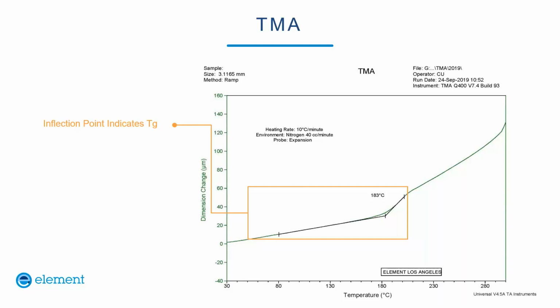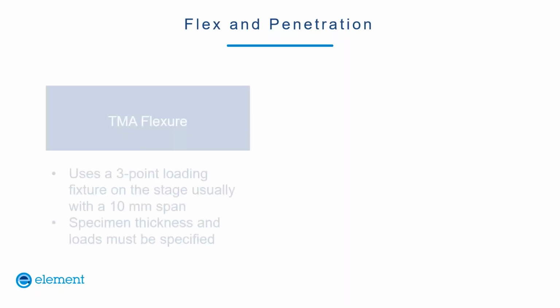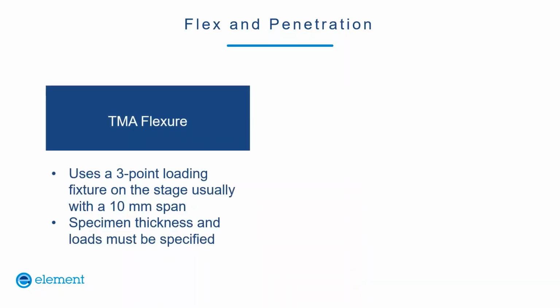TMA can also be used in a flexure or penetration mode. In each of these approaches, a larger force is applied and the probe deflects significantly. Usually we can do that with either a pointy probe, or we can do it using a 3-point bending fixture on a stage with a 10mm span. Specimen thicknesses and loads need to be specified. These methods are written into some specifications, but it's important to get the loads and the thicknesses right, because the ratio of load versus span is important, and if you're not consistent, you get wonky data.